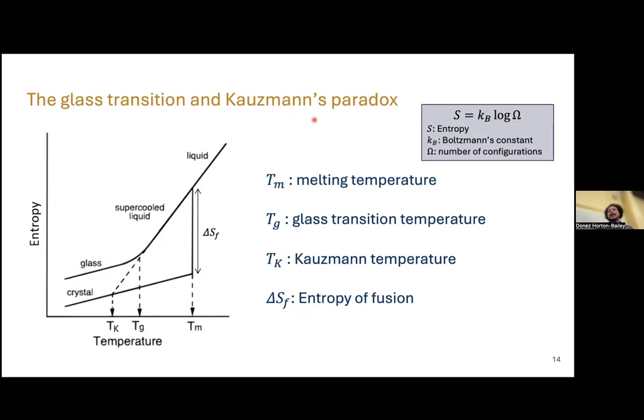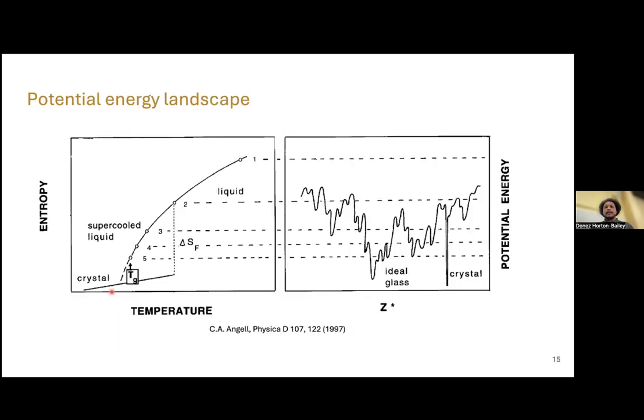There used to be this idea of a Kauzmann paradox. This scientist named Kauzmann theorized that, if I keep cooling, theoretically, I should be able to cool it to the point where my liquid has the same entropy as a crystal. This paradox was resolved by this idea of glass formation. So the glass formation actually prevents these two lines from ever actually touching.